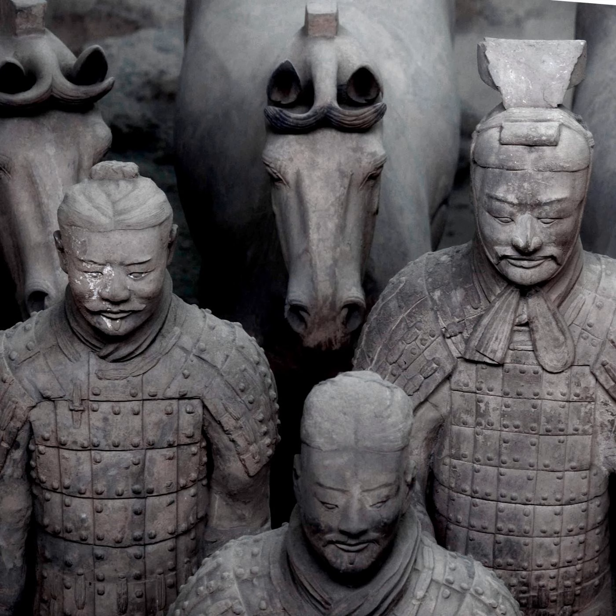So after that magic 800 degrees Celsius mark, some of the silica in the clay starts to melt into glass. Now remember, clay is mostly a compound called alumina silicate, right? So there's plenty of silica present in clay. It's not the only thing in clay, of course, but there's a lot of it in there. And so this melted silica, this melted glass, flows around the remaining clay particles, sort of locking them together. And of course, they're already held into place because of the sintering. And so this melted glass sort of fills in all the little tiny spaces in between the clay particles to create a much more non-porous material.